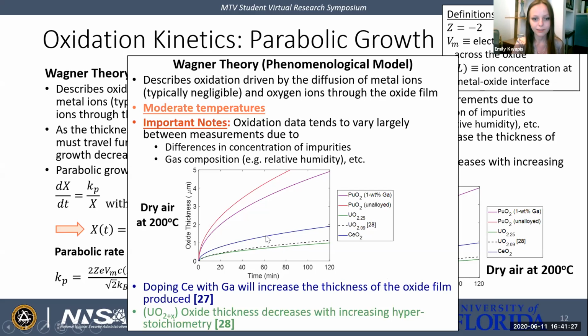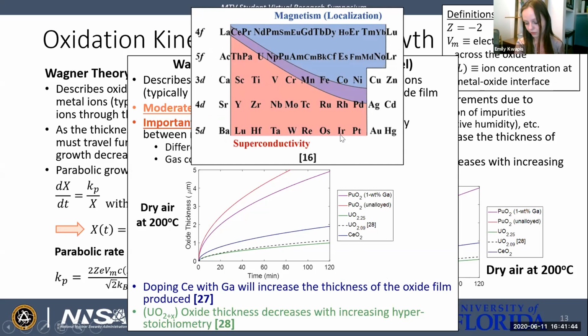But I do want to point out that with cerium, you can increase its thickness here by doping cerium with gallium. And that enhances the oxidation kinetics of cerium, which you didn't see with plutonium. But going back to this diagram here, that's exactly what you would expect to see. You dope cerium with gallium, you're shifting it closer to this transition between localization and delocalization, which is going to make it more reactive. While when you dope plutonium with gallium, since it was already on this transition, you were moving it off into the localization region where it would be less reactive.